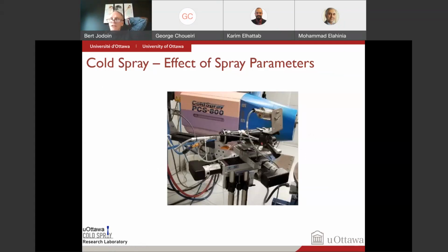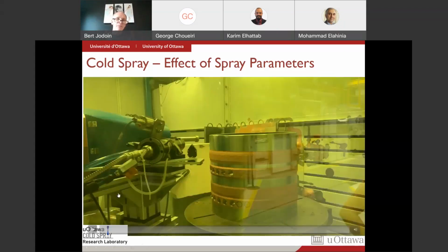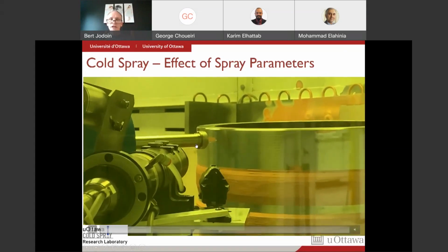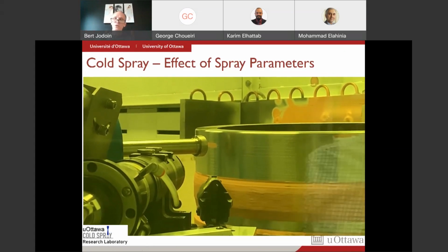We also have worked on the development of an enhanced system where we're using laser assisted cold spray. So we have a laser on the side that will shine directly where the particles will impact. And the reason is to preheat the substrate just before the particles hit the substrate to make sure that it's a bit more ductile. So you have an example here of the system. When you spray, this is a large cylinder, and we spray copper traces on top of it. So you have the laser here, and it shines just there to locally preheat just before we spray to enhance the ductility. So that's one way also to promote adhesion and promote deformation.